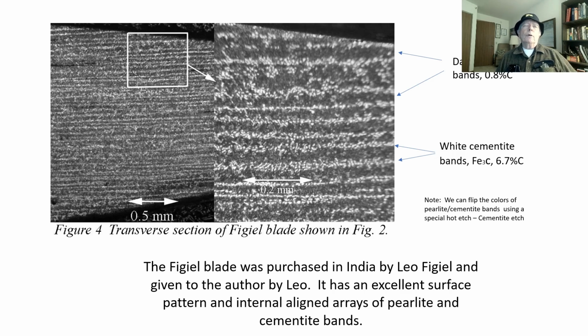Here's a picture showing a cross-section of the internal microstructure after polishing to a bare finish and etching it in a common etch used for steel. It's called nital. The Ni stands for nitric acid, and the tal stands for alcohol. Nital etches steel such that